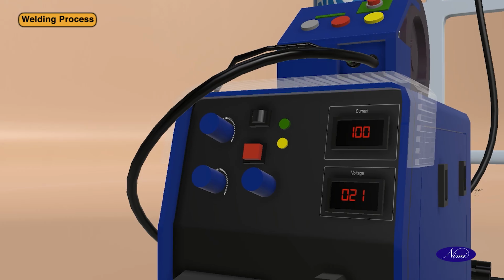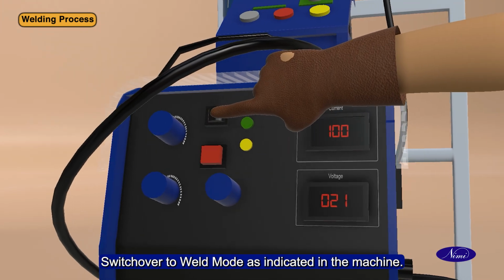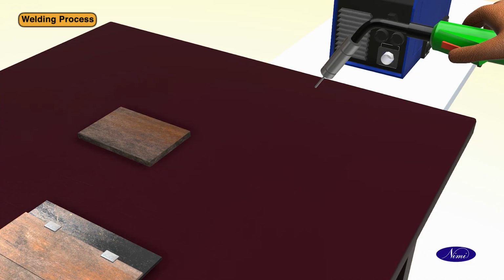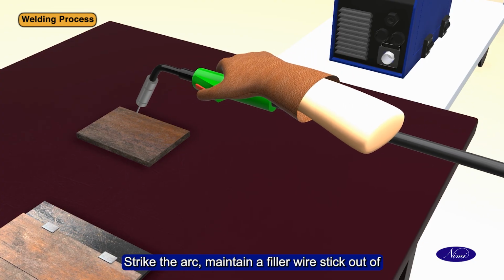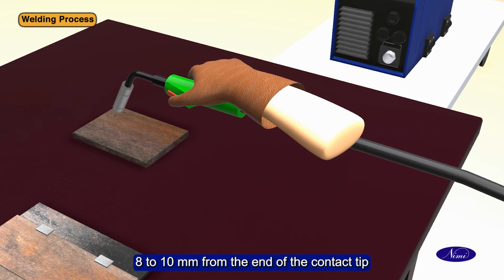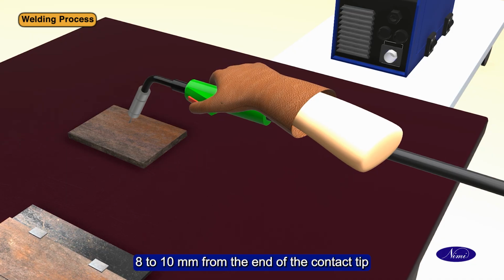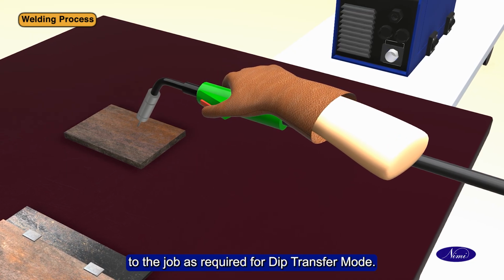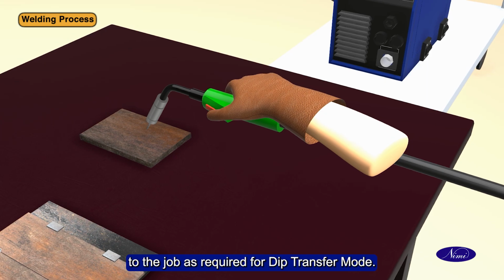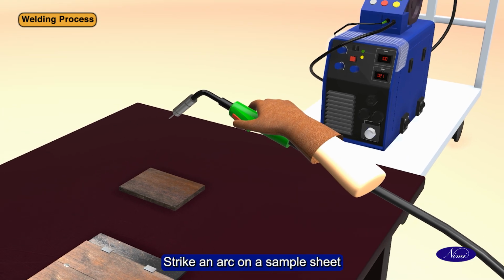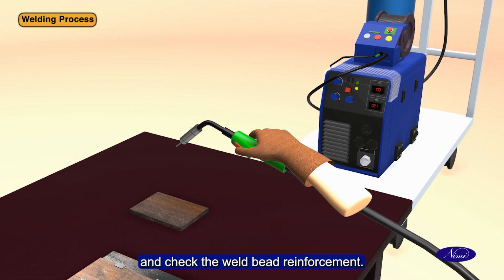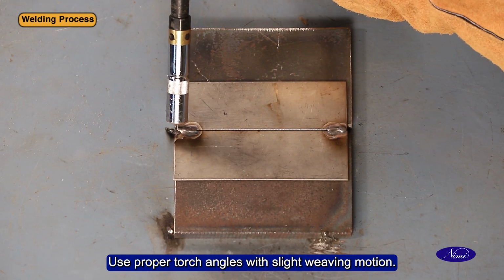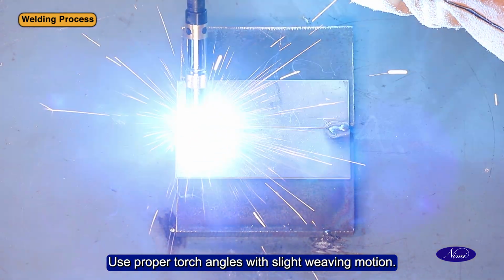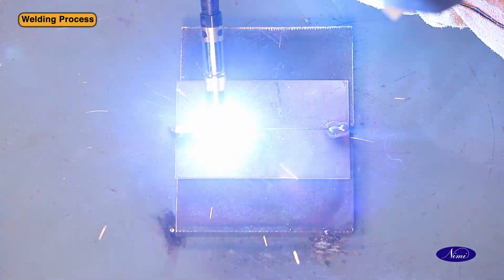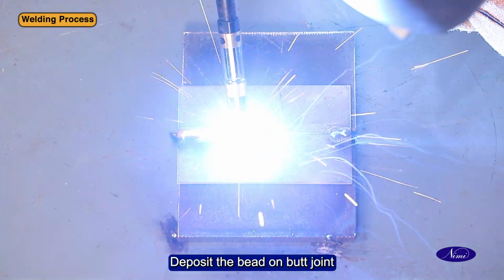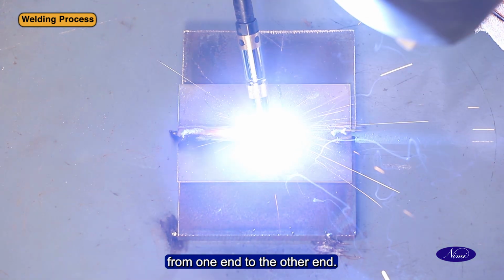setting. Switch over to weld mode as indicated in the machine. Strike the arc, maintain a filler wire stick out of 8 to 10 mm from the end of the contact tip to the job as required for dip transfer mode. Strike an arc on a sample sheet and check the weld bead reinforcement. Use proper torch angles with slight weaving motion. Deposit the bead on butt joint from one end to the other end.